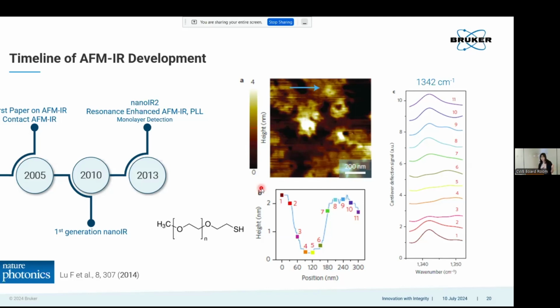And so here, this is just a proof of concept of a polyethylene glycol material. So there's 2 carbons bonded to oxygen, bonded to 2 carbons, repeated over and over and over again. And they made a monolayer of this material where you can see the difference between not being on the material and being on the material is only 2 nanometers. And as they take the spectra over this, you see that when you're on the material, you get your signal. When you're off of it, you see nothing. And then when you're on it, you see a signal again.